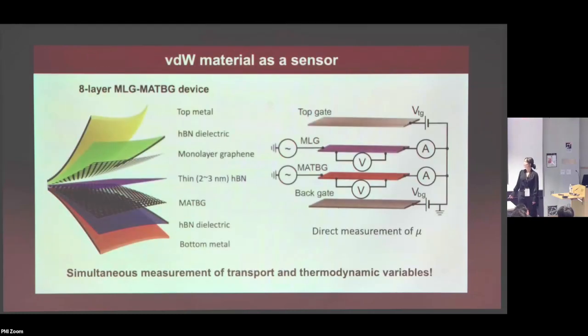Okay, so how are we actually going to measure this kind of quantity? Of course, there are so many other techniques that are very fancy, but imagine you don't have those machines. How can we achieve that? We thought of a technique where we can directly sense the chemical potential of this magic angle twisted graphene layer using another monolayer graphene that's very close by. They're only separated by a very thin dielectric, okay? And they're all separately contacted as Hall bars and gated.